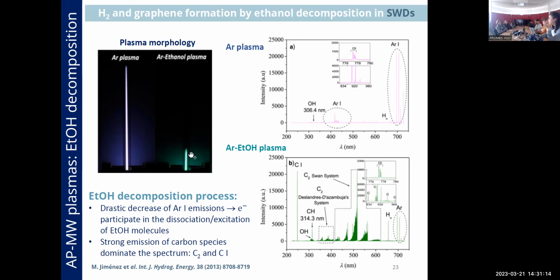What about the color? Since the plasma emits radiation, and the color changes, the radiation changes. Why? Because we are having different excitations in our plasma. Here you have the emission spectrum of typical argon plasma with argon emission lines. And when we introduce ethanol, we observe that the intensity of these argon lines decreases, and some of them even disappear. Why?